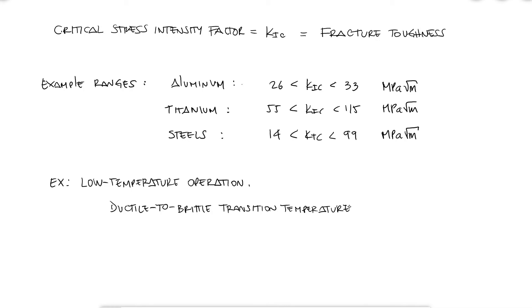And even then, tables of transition temperature for different materials are not commonly published, mainly because the values vary a lot. A key indicator, however, is the ratio between the yield strength and the ultimate strength, because a higher ratio means that the ability to absorb energy in the plastic region is low and therefore there's a higher chance of brittle fracture.